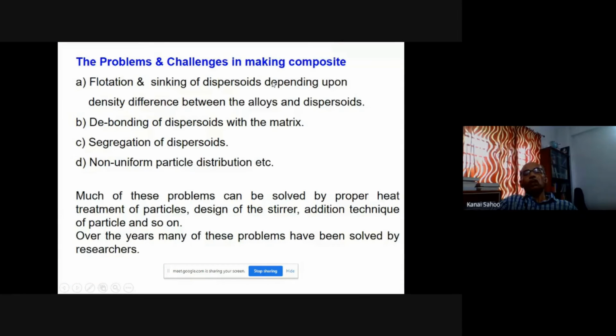The problems in composite making, as I told you, are flotation and sinking. If you use fine particles, they will float. If you use heavy particles, they will sink. So debonding is a major issue, as are segregation and non-uniform structure. But all these problems can be solved if you properly design the Rheo cast parameters, stirrer, addition technique, and the particle and the matrix. You have to see what elements will wet; the wetting will be more for the added particles. You have to see that.